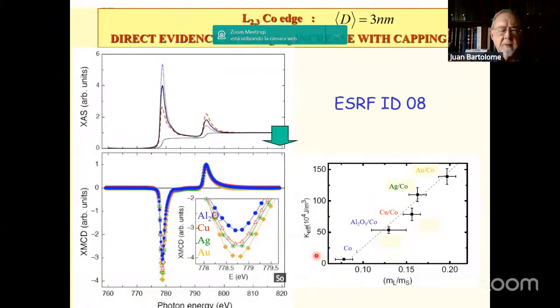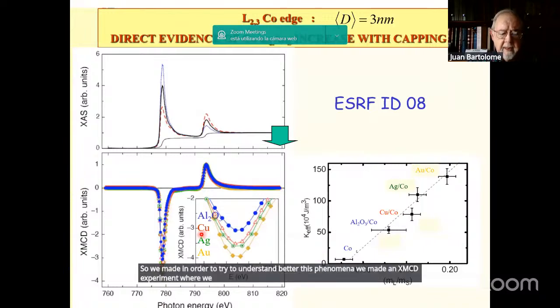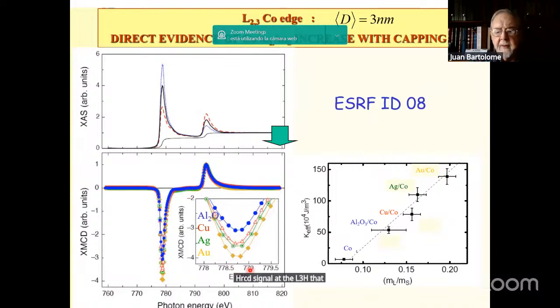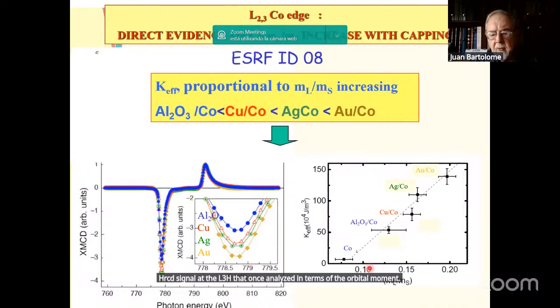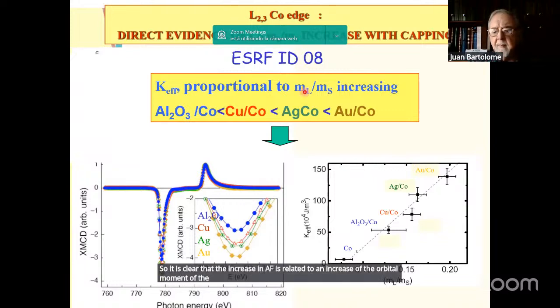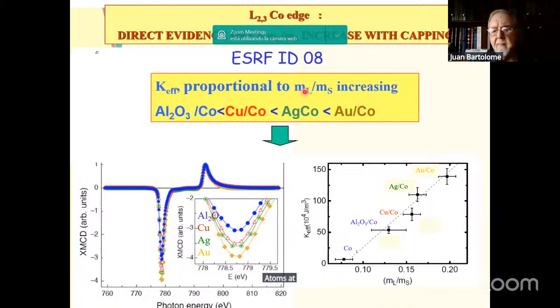So, in order to try to understand this phenomenon better, we made an XMCD experiment at the L2,3 edges of cobalt, where we see that there is an increase in the raw XMCD signal at the L3 edge that, once analyzed in terms of the orbital moment, could be correlated linearly with the increase of effective anisotropy. So it is clear that the increase in K_eff is related to an increase of the orbital moment of the cobalt atoms at the surface of the particles.